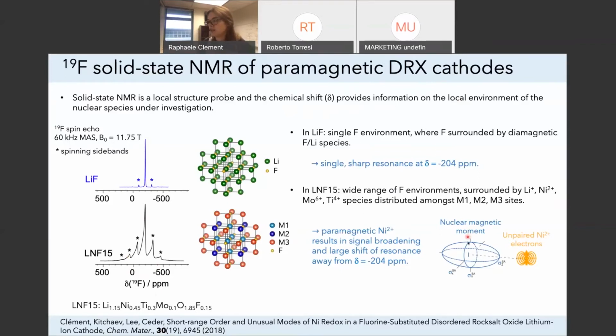And so this interaction is very strong. This is your fluorine, this is your nickel. This interaction is very strong and leads to broadening and a chemical shift. It also allows us to gain a lot of information on the local structure of these materials based on the chemical shift. But the complication here is that we have a disordered structure and therefore a large number of environments with overlapping signals.